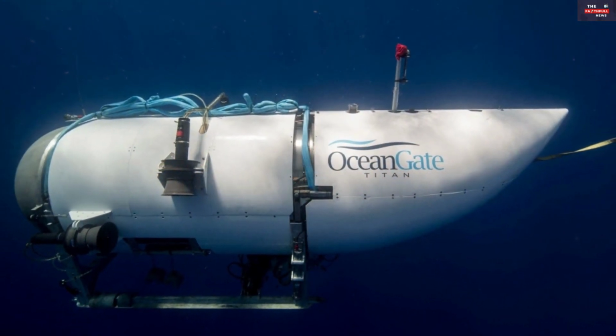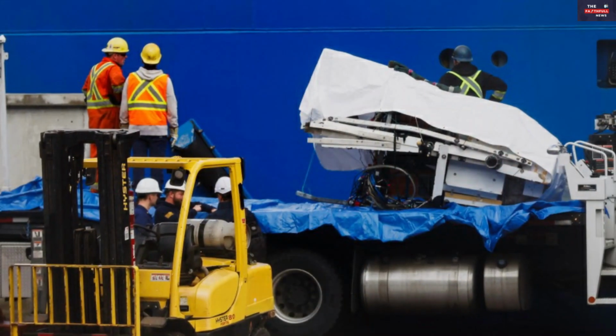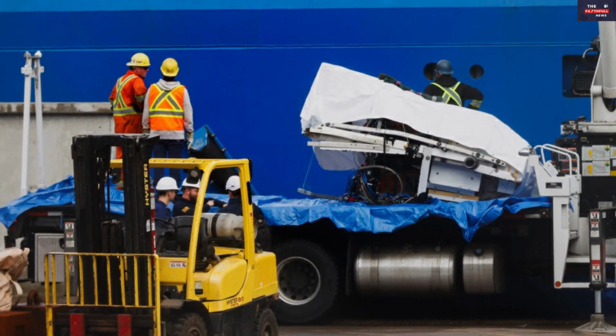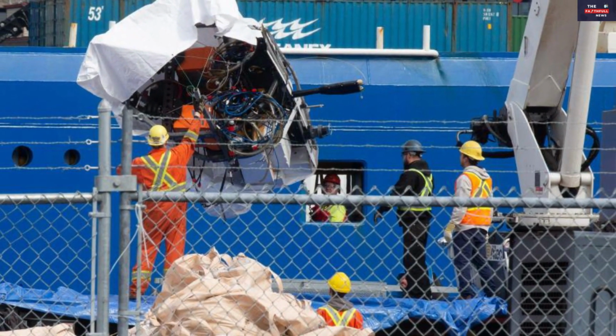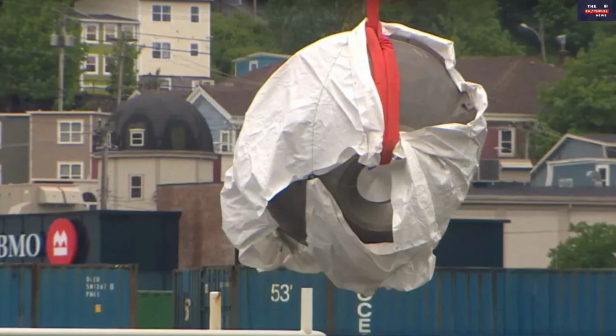Was there excessive heat on board the sub? Investigators looking at the mangled metal debris will also search for signs of excessive heating, corrosion, and buckling, he said. Dr. Graham Jones explained, has there been excessive heating, or corrosion, or buckling? Distortion of joints and fittings. But an issue investigators could face is differentiating between problems that were already on the submarine prior to its launch, and defects which formed on the vessel after implosion. Were there any defects from before sub went down? Dr. Graham Jones said, there are 3 timelines, before the incident, during the incident, and after the incident.